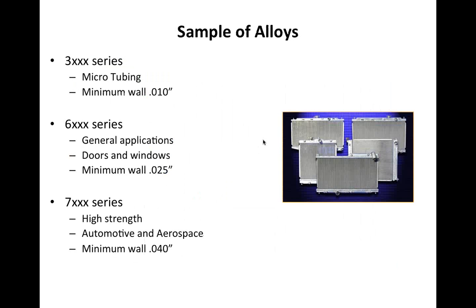One quick thing I'd just like to touch on. What most extruders realize is that if you're extruding 6000 series alloy and you have a customer that wants to extrude a 10 thou wall, or probably a 9 thou wall, it's impossible to extrude that size of wall with 6000, which takes us to maybe a 3000 or 1000 series alloy, which has a lower flow stress, which will allow us to extrude a thinner wall.